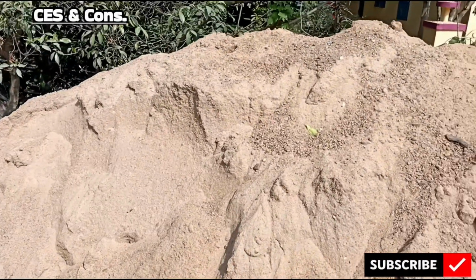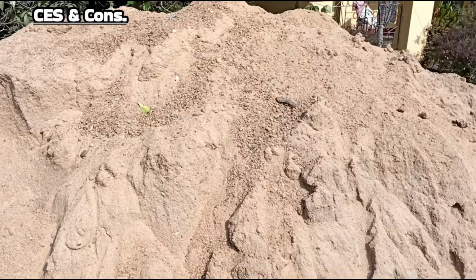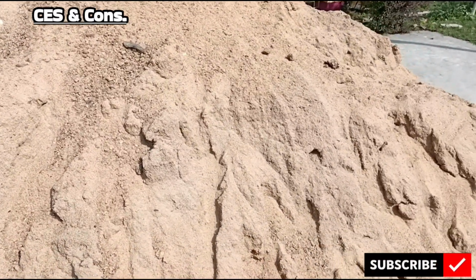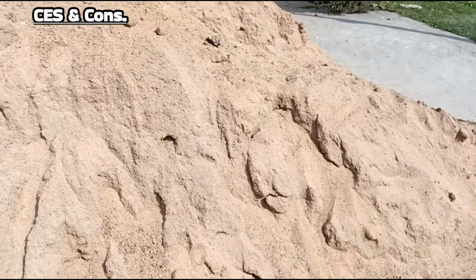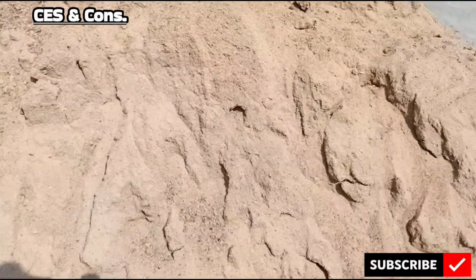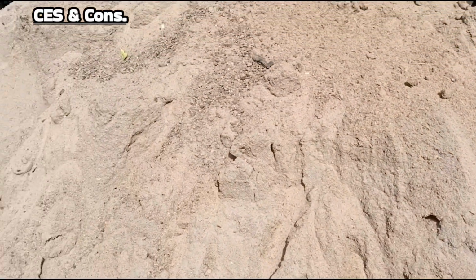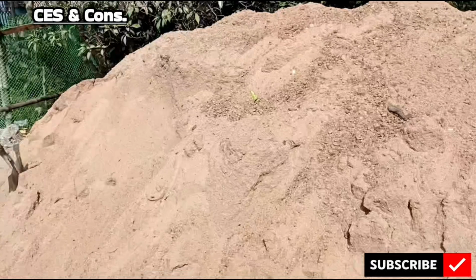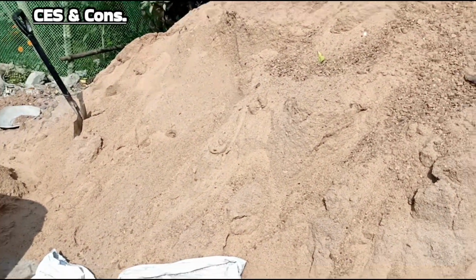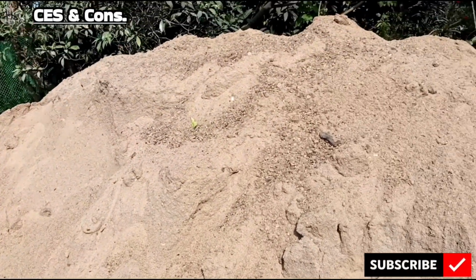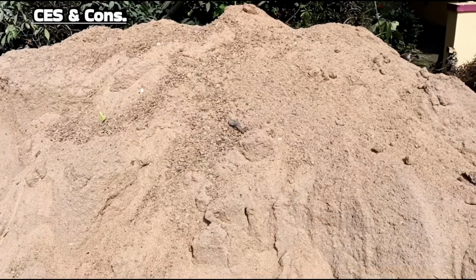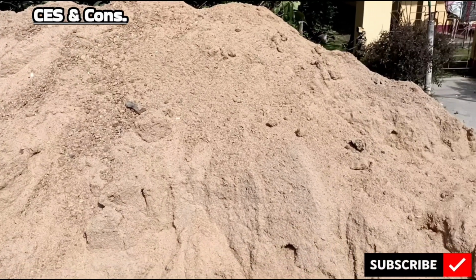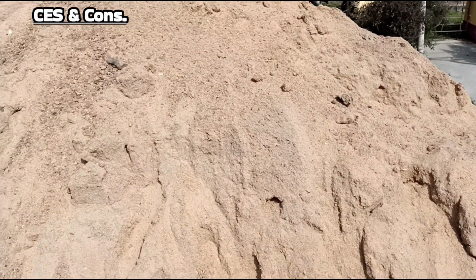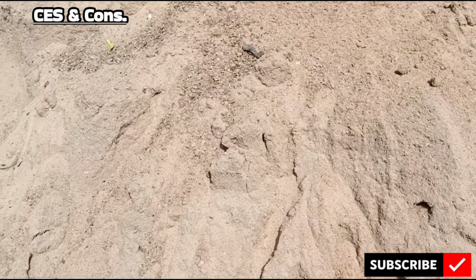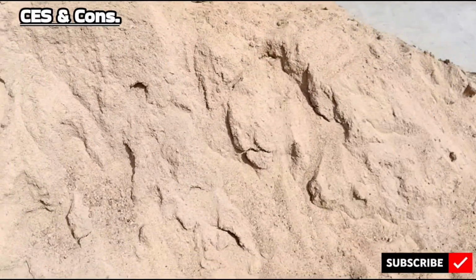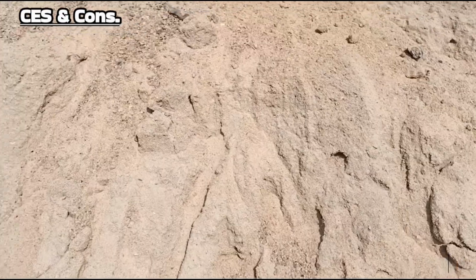Sand. The sand used for plastering should conform to IS 383-2016, specification for fine aggregates. It should be clean, well graded, free from organic impurities, silt and clay. The fineness modulus should lie between 1.5 to 3.0 for plastering sand. Water. Water should conform to IS 456-2000 requirements: potable quality, free from harmful salts, organic matter or any oils.